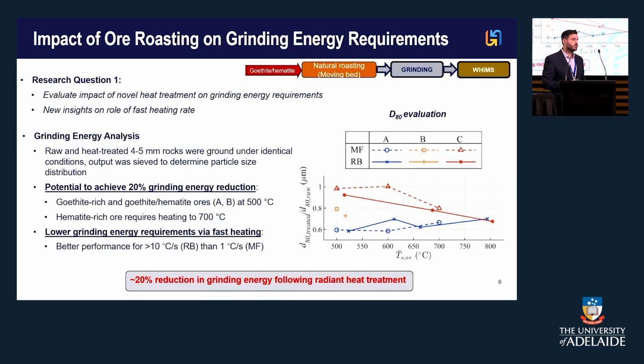Now, three research questions. The first was: can we reduce the grinding energy? We believe that for most of the ores that we have tested in the last three years, yes, we can. As you can see, the high flux radiation method has strong potential to reduce the grinding energy, on average up to 20%. Where hematite is the primary ore, we have to roast up to 700 degrees, but when goethite is in the mix, this is really mild heating, in the order of 300 to 500 degrees, to reach this benefit.